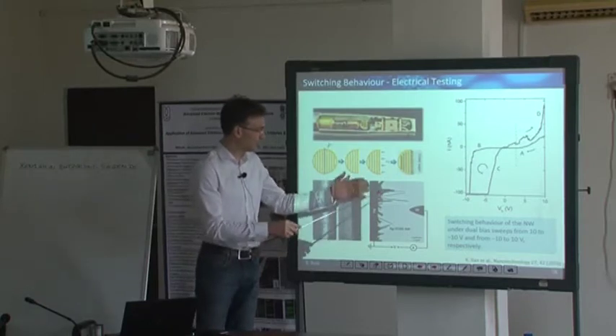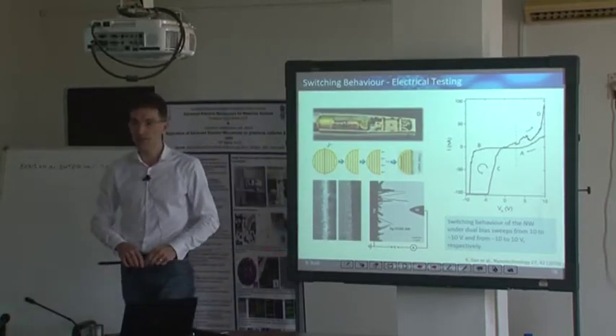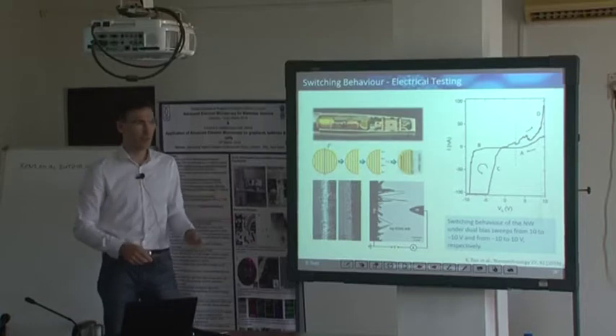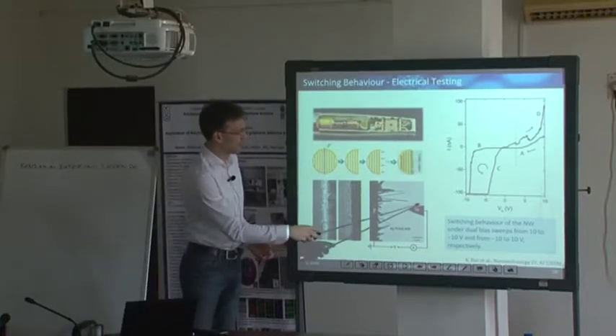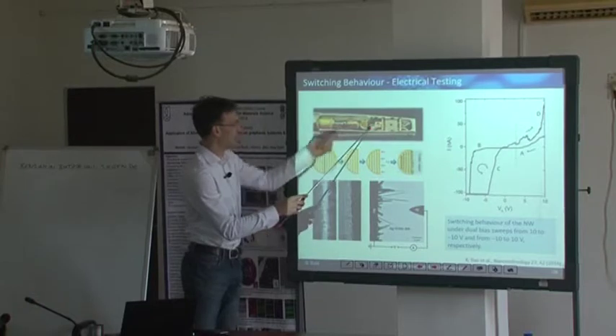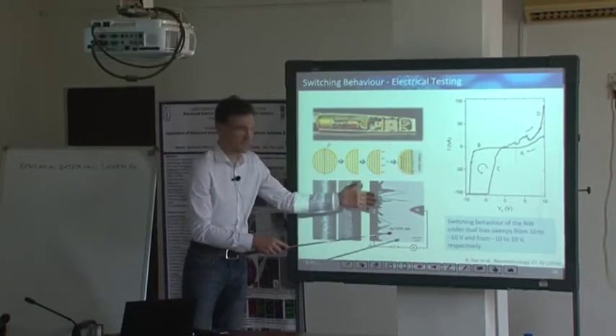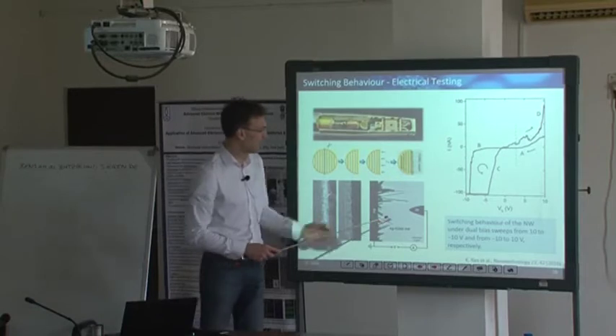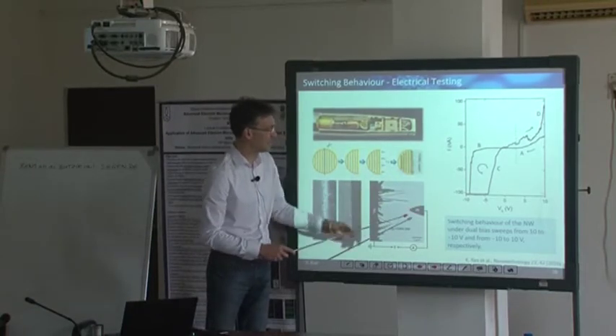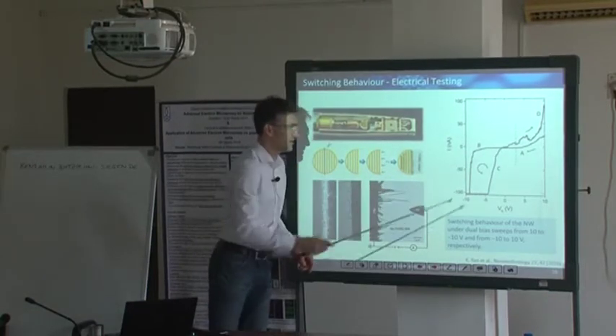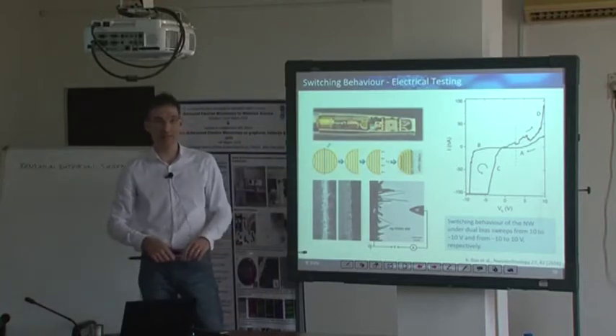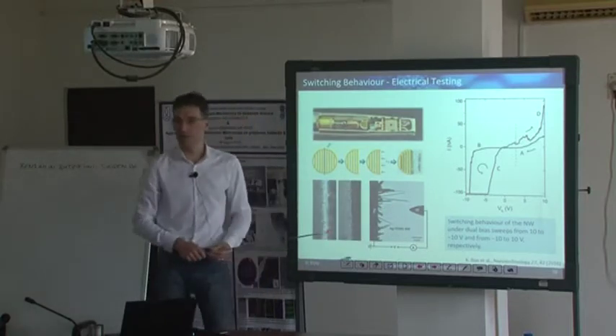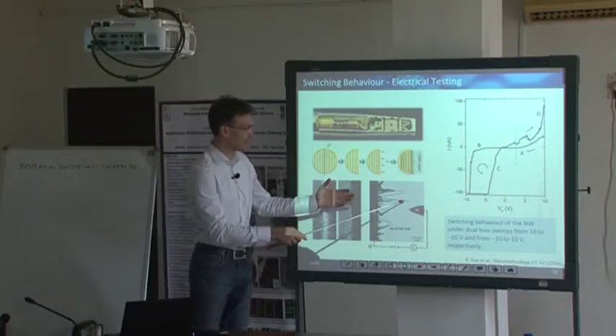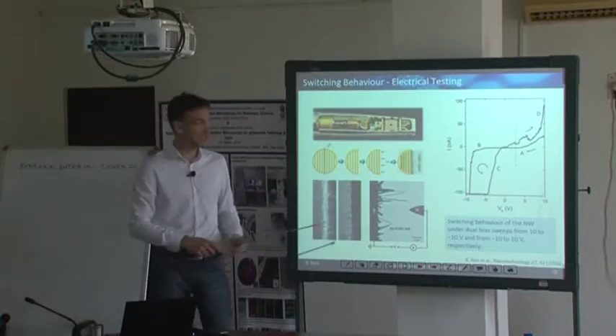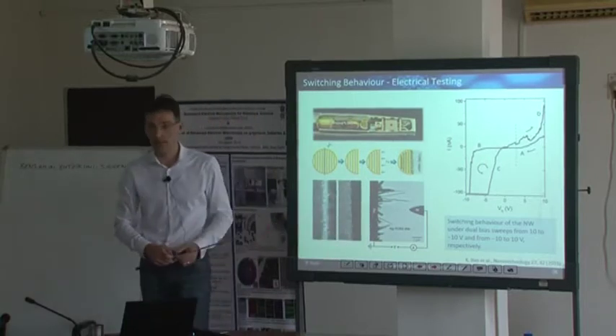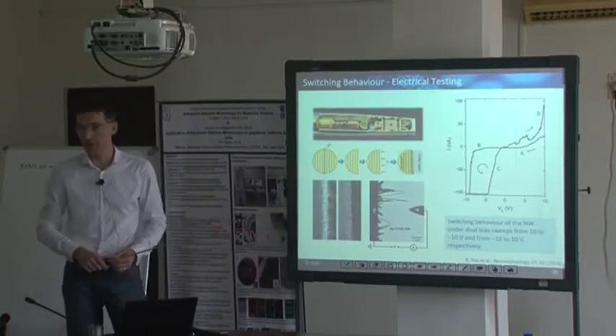The question was, people want to make use of those switching materials to realize circuits on a localized scale, and so we approached with this metal tip here on the right-hand side, or the other way, we approached this metal tip with our sample by just moving our sample, and just by contacting individual nanowires, we were able to demonstrate this hysteresis, so this switching behavior depending on the applied current. So you can do that on the localized scale. You can directly contact individual nanostructures. This is what you can do in a scanning electron microscope as well, just by using such nanomanipulators, for instance.